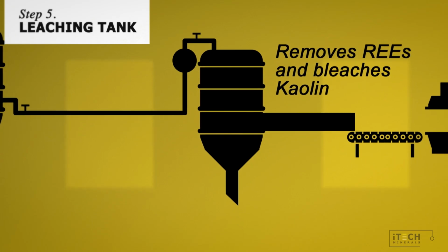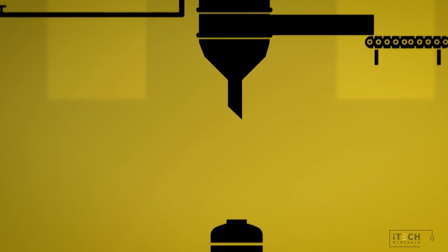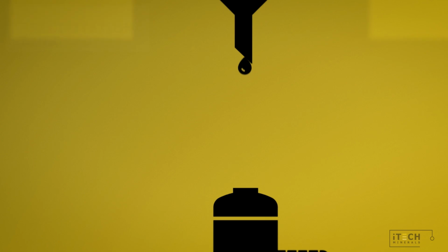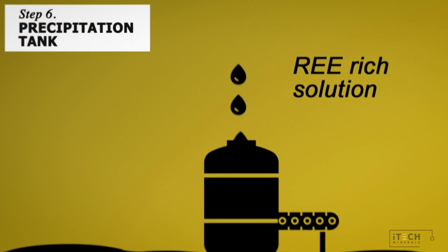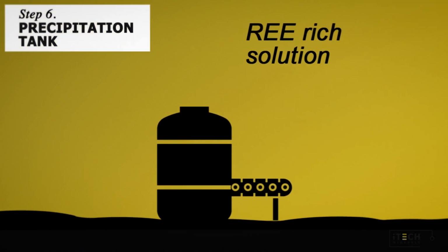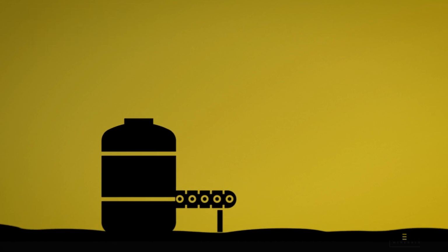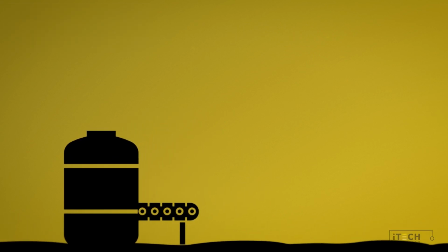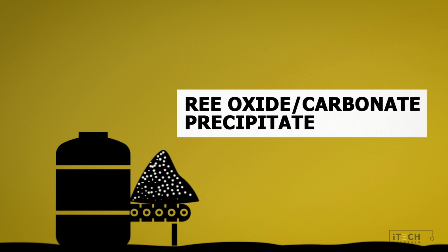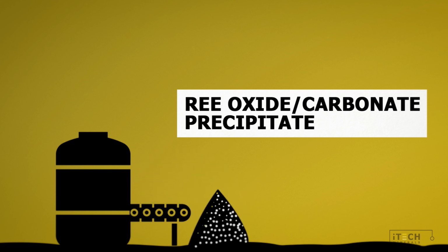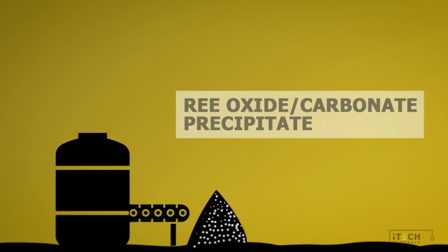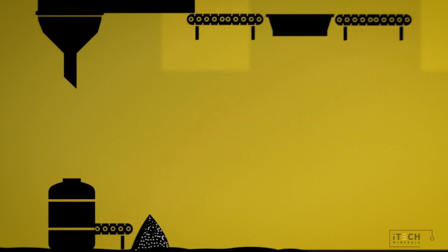You put that into tanks and you leach it off with an acid-rich solution. That acid-rich solution pumps off to a precipitation tank where you remove the impurities, and then you precipitate out a clean rare earth element concentrate, either as oxides or carbonates. Now that's your first product that you can sell. The second product is still left in the leaching tanks. You pump that over to a filter press, and that's your bright white high purity kaolin material.